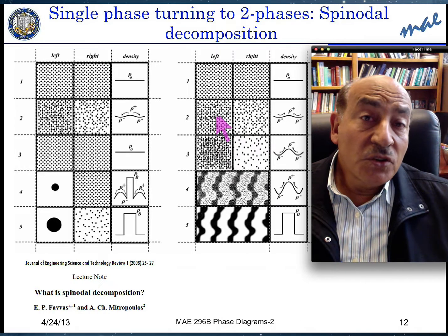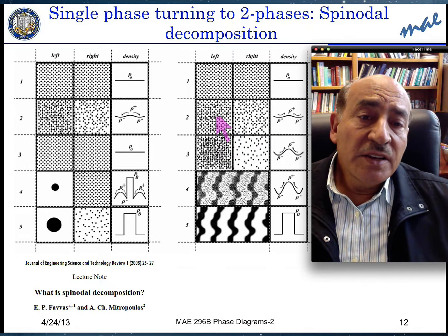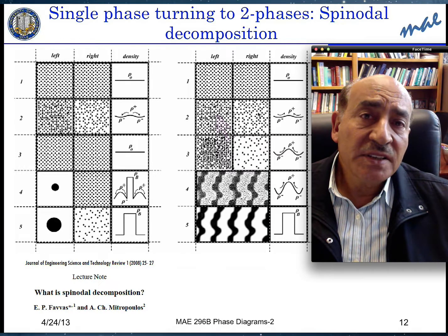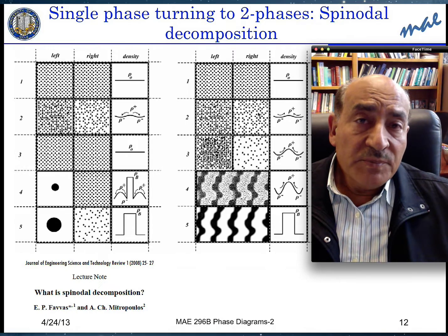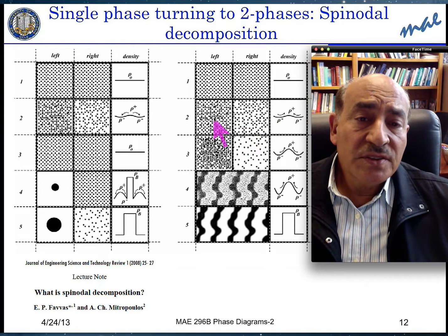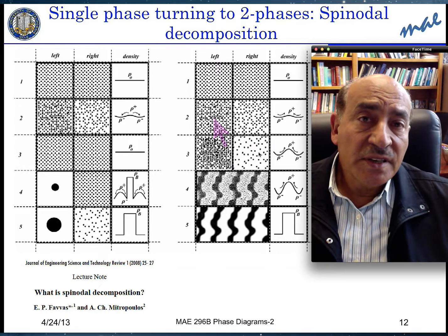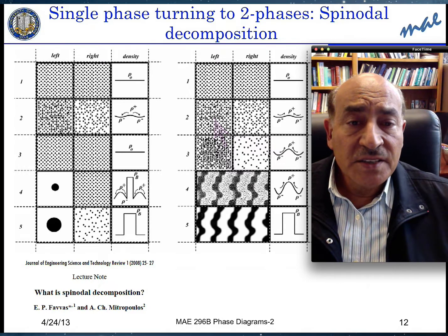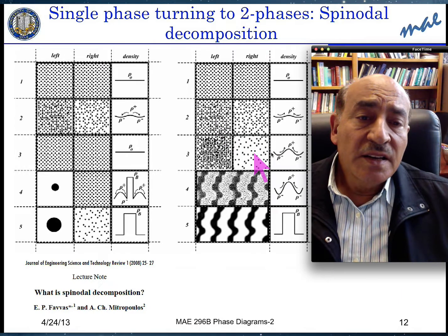Normally, in a normal situation, we would have Fickian diffusion which will push the higher concentration back into the lower concentration and make it more uniform. But because the delta H mixing makes them like each other, whenever this guy goes to the other side, it feels more comfortable here and it wants to stay. So it leads to a phenomenon that is called uphill diffusion. In other words, diffusion not down the concentration gradient, but up the concentration gradient, as you can see here.